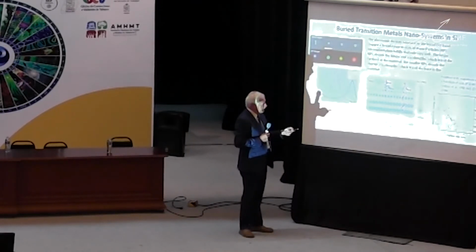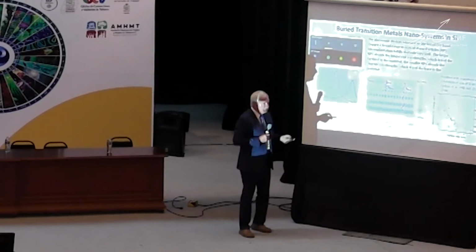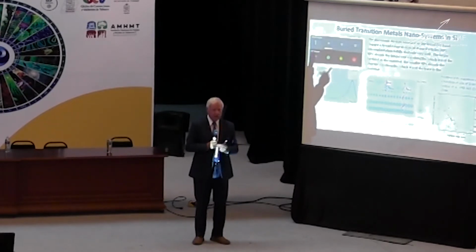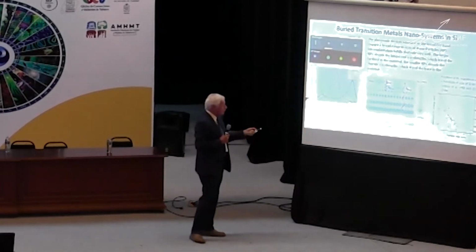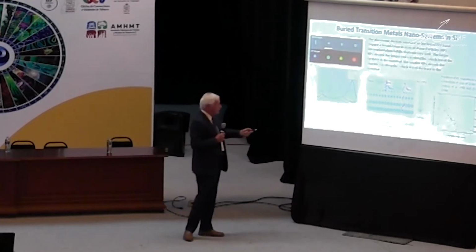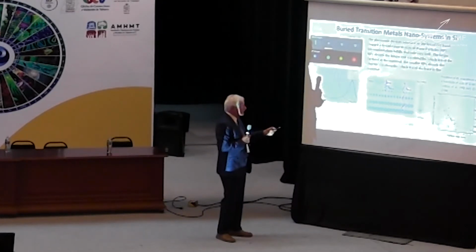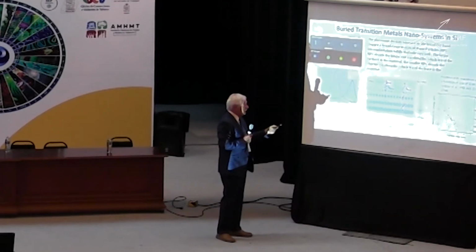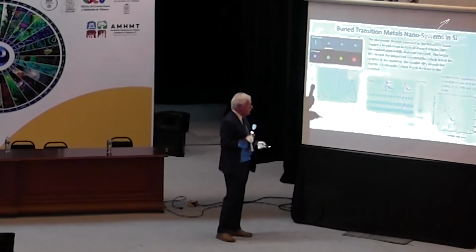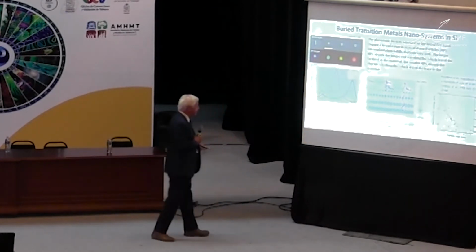Now, why do I want to do this? It turns out that the larger the nanoparticle is, the larger the wavelength that it can intercept, and the larger the wavelength that it re-emits. The smaller the nanoparticle, the smaller the wavelength. Small wavelength means higher energy. So the higher energy photons that are coming into this material get absorbed right here. The lower energy photons of the longer wavelength get absorbed down here, and intermediate photons are in the middle. So what does that do for us?